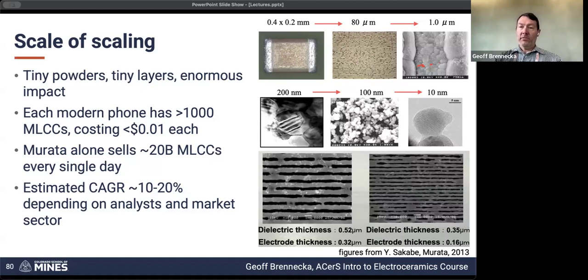At the same time, as we'll talk about in a little bit, you don't want the grains too small, because then you start to lose performance. So you'll notice that the electrode grains are much, much larger. Part of that is because it doesn't matter as much, and part of it is because most of the electrodes that we're using are going to sinter at lower temperatures than the dielectrics, so the mobility is going to be higher. And so we just end up with bigger, fatter electrode grains.